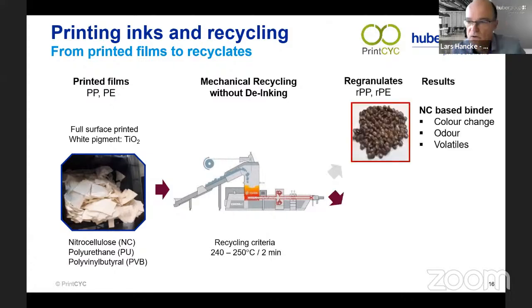And with the nitrocellulose, we found that we get this type of regranulate. It is dark brown, a strong change in the shade, because the binder decomposes. It breaks down into smaller particles, and these undergo follow-up reactions that result in this type of shade. And we do not only have the change in the hue, we also have a strong odor related to the regranulate, and also we find a high amount of volatile byproducts. The machine was smoking and fuming. It was not really nice to watch that and to smell that as well.